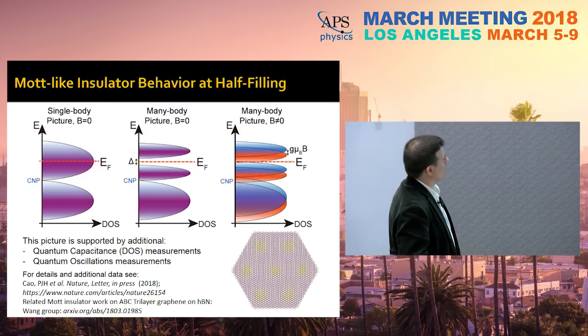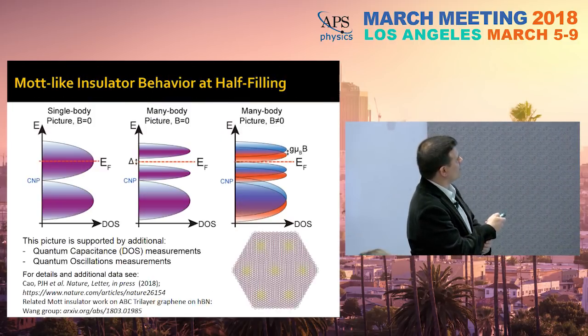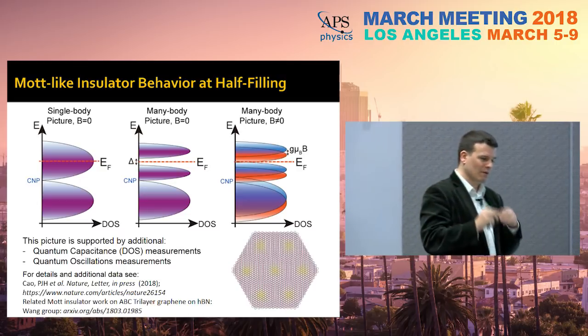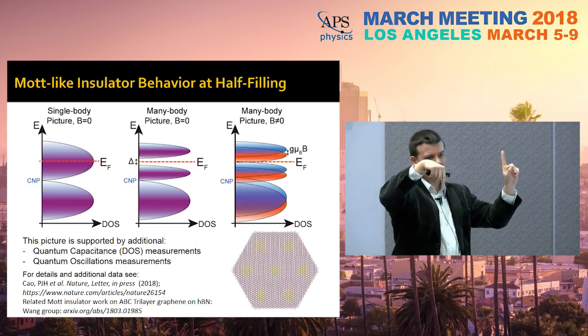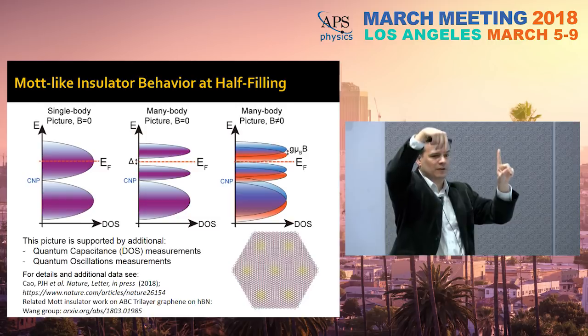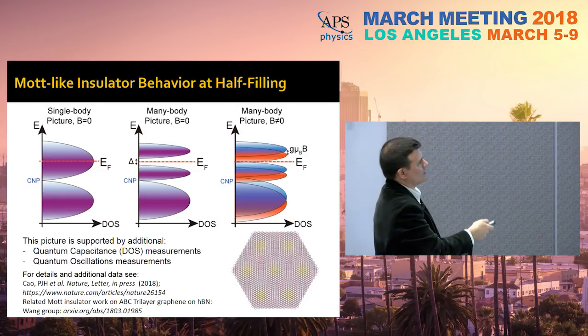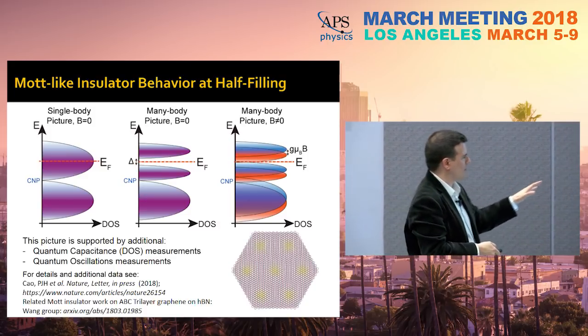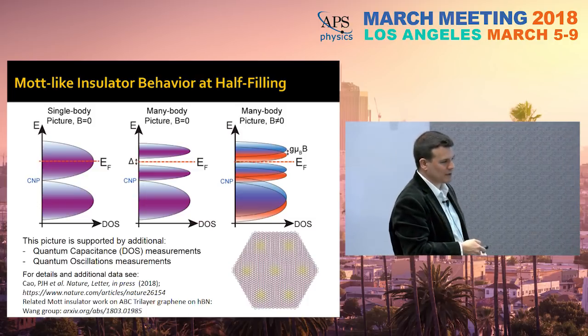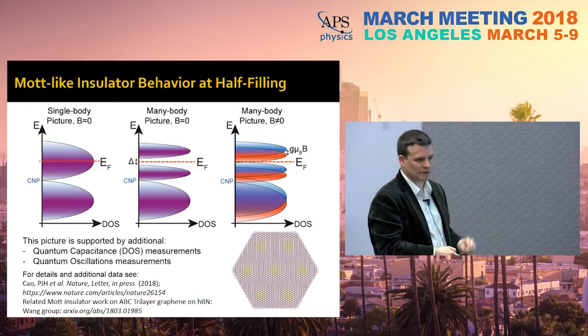And the way we understand this is the following. In a single-body picture, okay, you have the two bands. You have no band gap because this is a Dirac system. When you are at half filling, you develop this many-body gap state. Okay? It turns out that this system very likely consists of spin singlets. And when you apply a magnetic field, parallel or perpendicular, because the important thing is the Zeeman effect, you polarize these singlets, and when the Zeeman splitting closes this gap, then you start conduction through the system. Okay? This picture, again, we have a lot more data that you can look at in the paper. It's supported by additional quantum capacitance measurements of the density of states, by quantum oscillation measurements, and by many other things. Okay? So you can look for details in the paper.